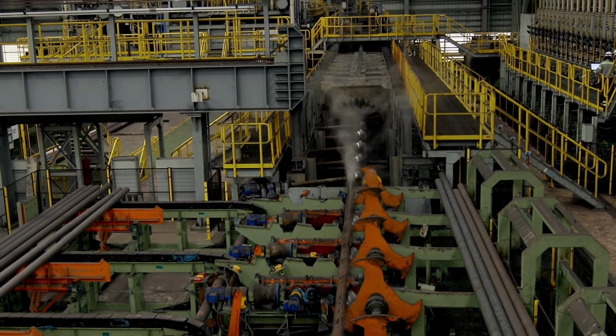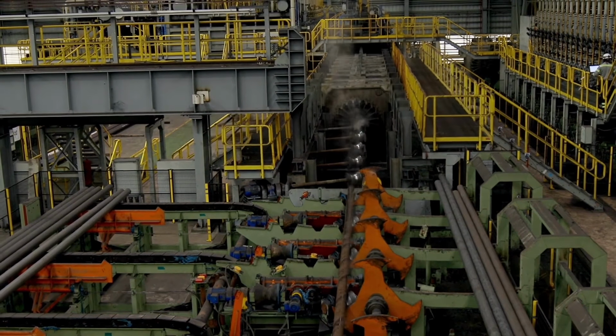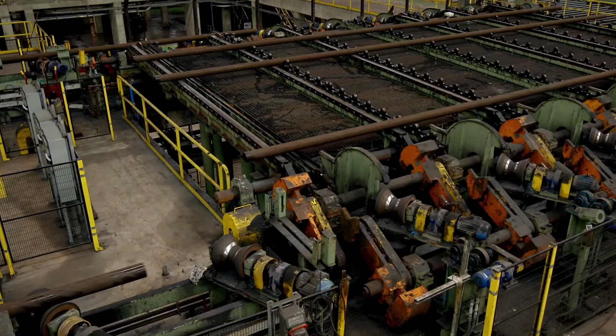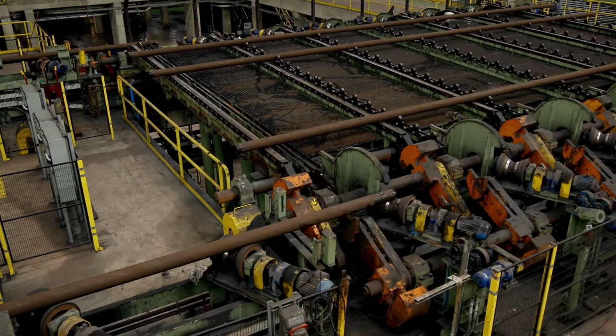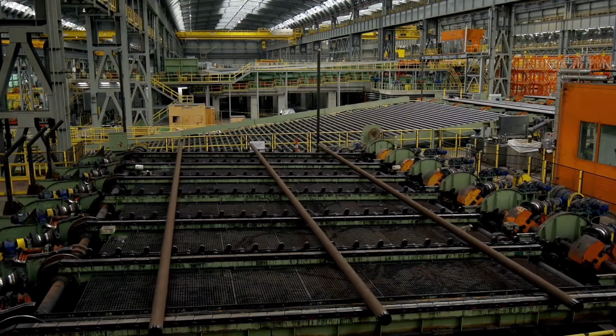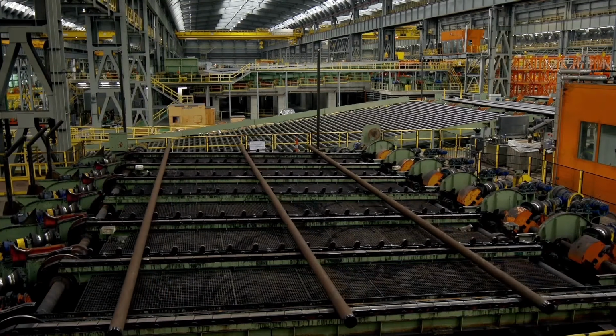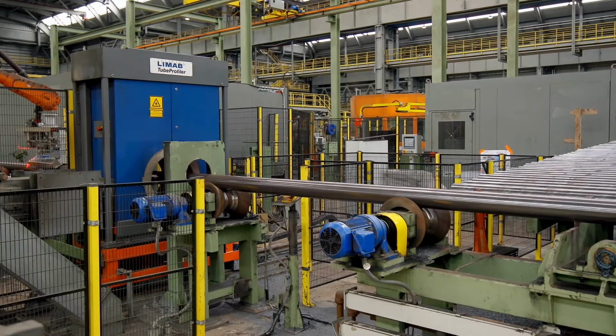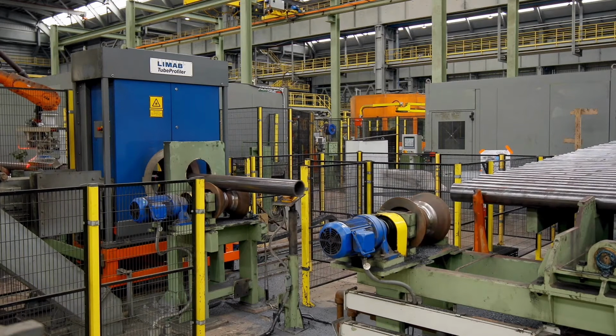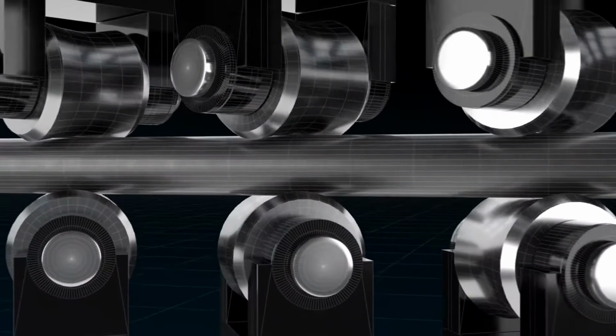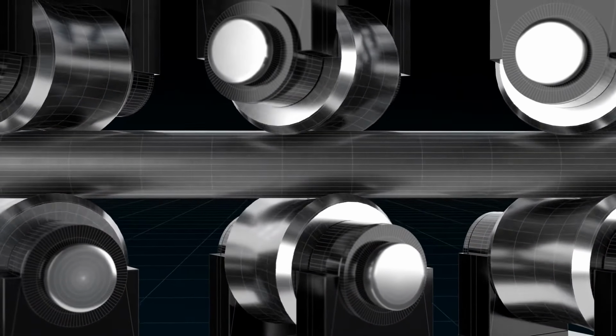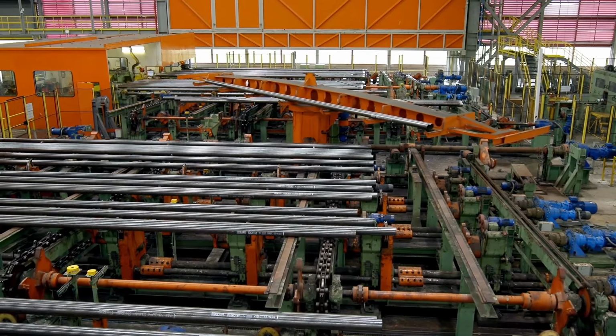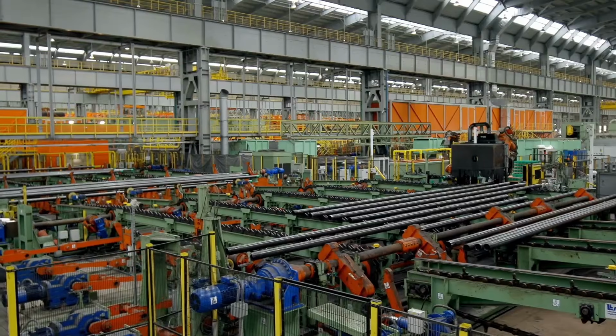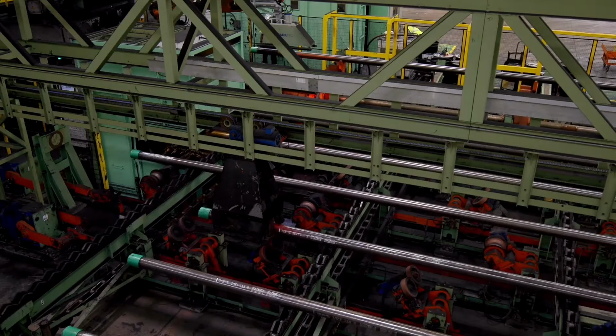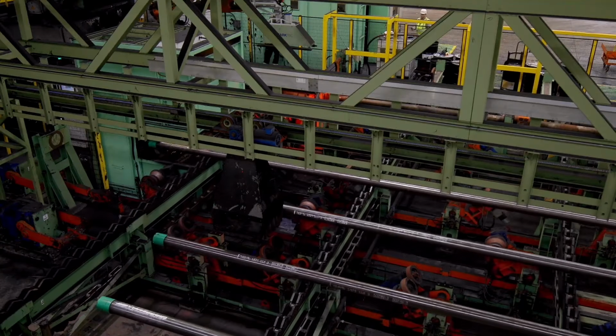Then heat treatment. Austenitizing furnace above the transformation point, water quenching at high pressure down from around 900 degrees Celsius to make martensite, tempering to restore ductility. Straightening machines correct ovality within a hair. Every single pipe goes through hydrostatic testing, electromagnetic inspection, and ultrasonic wall thickness scanning. Because a pipe that fails 4,000 feet down is a pipe you cannot recall.